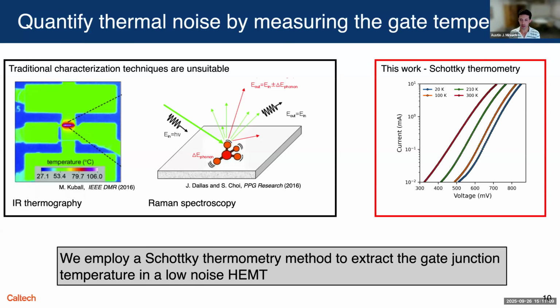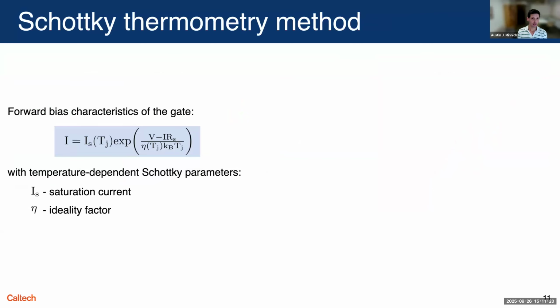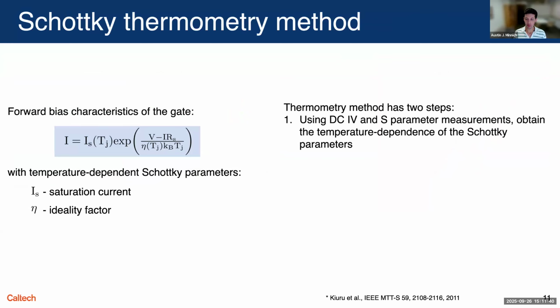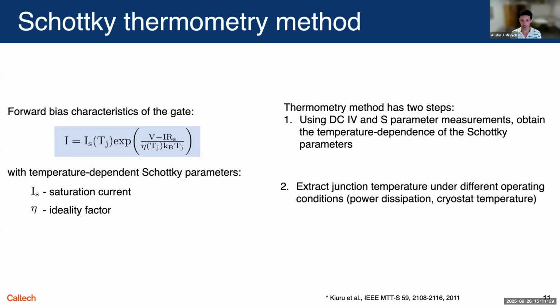What we did instead is use Schottky thermometry, which relies on the temperature dependence of the Schottky characteristics of the gate junction to extract temperature under different conditions. So the Schottky thermometry method relies on the temperature dependence of this familiar Schottky equation. And you can see the saturation current IS as well as the ideality factor eta both have a temperature dependence in them. And so you can exploit that to get a thermometry method. So in the first step, you use DC current voltage, or IV, characteristics, as well as microwave S parameter measurements to essentially calibrate these temperature dependencies. And then with that, you can extract the junction temperature under different conditions, for instance, different biases or cryostat temperatures.